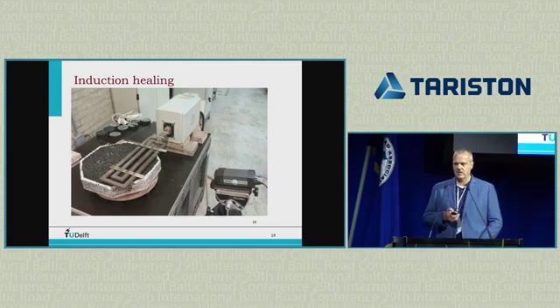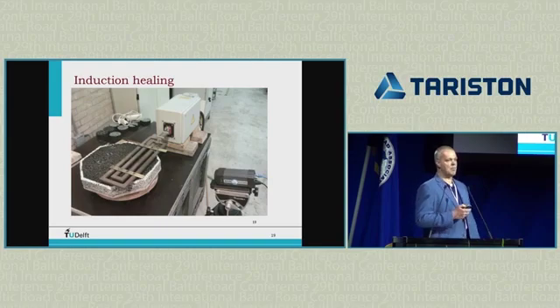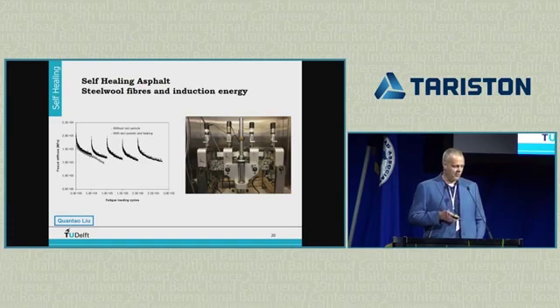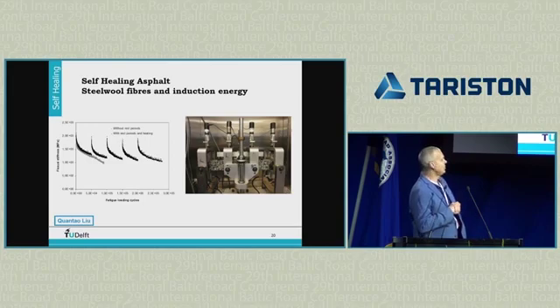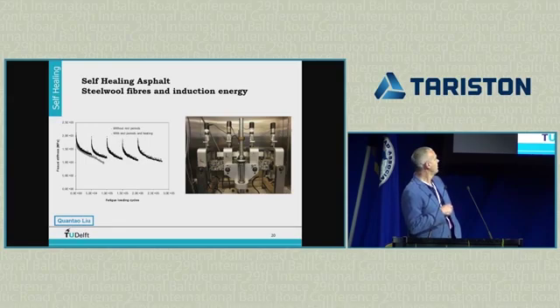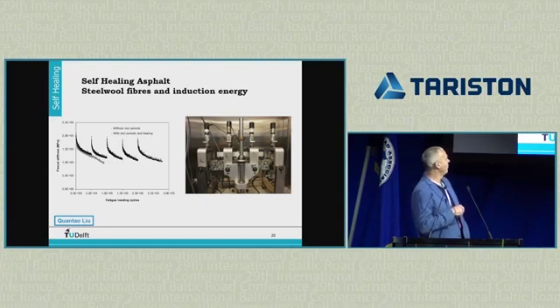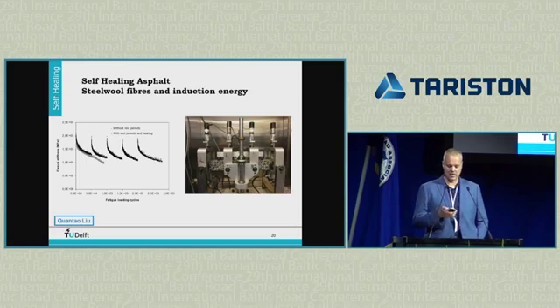So actually, we did a lot of tests on these materials. We did aging of the samples in the lab, damage them, heal them again, and then see what properties we get back afterwards. So this is an example of a four-point bending fatigue test, where we plot on the vertical axis the flexural stiffness, and on the horizontal axis the amount of cycles that we do. And you see, if you do the cycles, your stiffness will decrease if you do nothing. And if you stop the test here, heat up the sample, your stiffness will come back, and you can do this test over and over. So you damage your sample, heal it, and you can test it again.